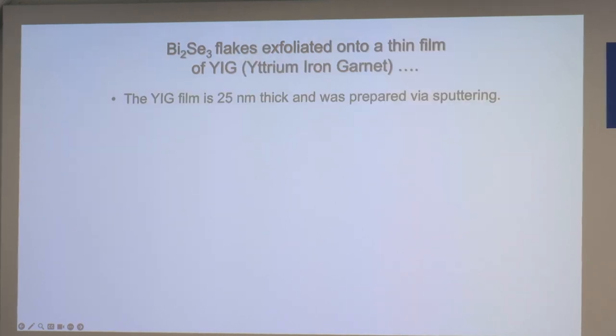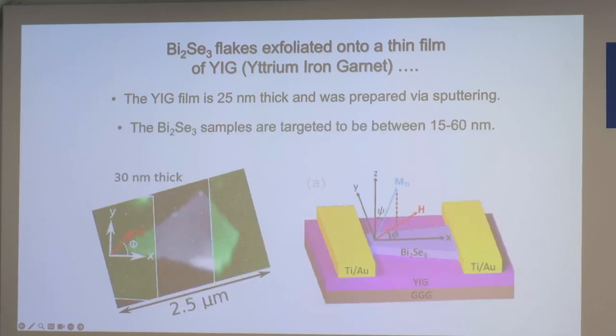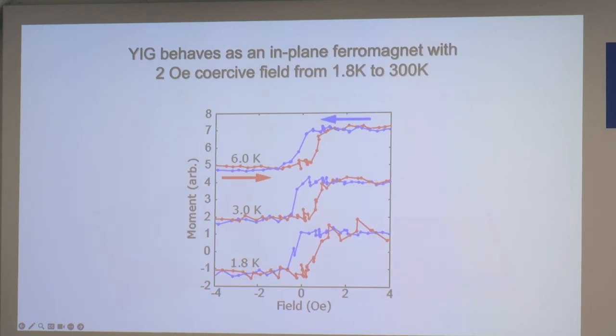Okay, so we exfoliated bismuth selenide onto YIG. YIG, we sputtered these. It's a thin film. This is what the samples looked like. Okay, this is a false color green, but this is where the leads are, and it's just a flake that's a couple microns in size. And then we rotated the field from out of plane to in plane. And just to start with a characterization of the YIG, this is a magnetic material in itself. It's not conducting, and so we looked at just the magnetic moment in a magnetic property measurement system. But you can see that the YIG has a coercive field of about 2 oersted. So the YIG switches its magnetization at about 2 oersted, which is a very small field.